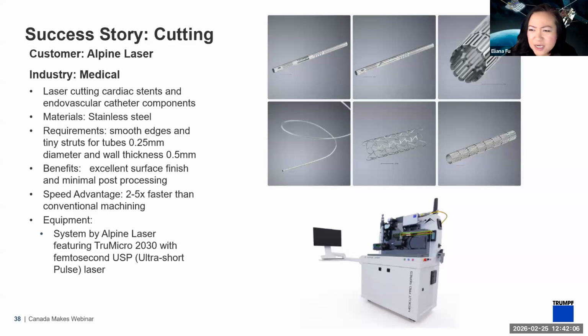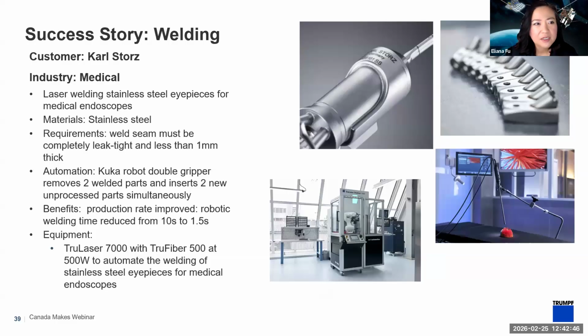So this benefits from using the laser: really excellent surface finish and minimal post-processing. The speed is an advantage, 2 to 5 times faster than conventional machining. And then they use our laser and package that into their own machine and put their own label on it. But these are the kinds of things that you'll see. They do a lot of work in North America, and you can see that's a kind of ultra short pulse. In this case, it's a femtosecond laser that they use, and then they have a process to basically hold the material and do that. Oh, it moved by itself.